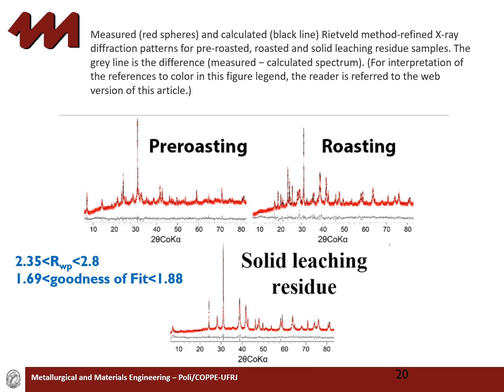The quality of the refinement was analyzed by the mathematical parameters Rwp and goodness of fit, which indicate the quality of the refinement, and they were in the range from 2.35 to 2.80 and 1.69 to 1.88 respectively. These values are indicative of good quality refinement. The visual inspection of the obtained and calculated diffractogram spectrum, as well as the residual difference of the measured and calculated diffractograms, also present a very good fit.